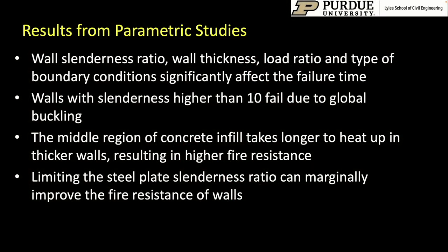The results from the parametric studies were as follows. We found that the wall slenderness ratio, the wall thickness, the load ratio, and the type of boundary conditions significantly affect the failure times. Walls with slenderness ratios higher than 10, which means that the story height divided by wall thickness ratio greater than 10, fail due to global buckling. The middle region of the concrete infill takes much longer to heat up in thicker walls, resulting in very high fire resistance. And limiting the steel plate slenderness ratio can marginally improve the fire resistance of the walls.